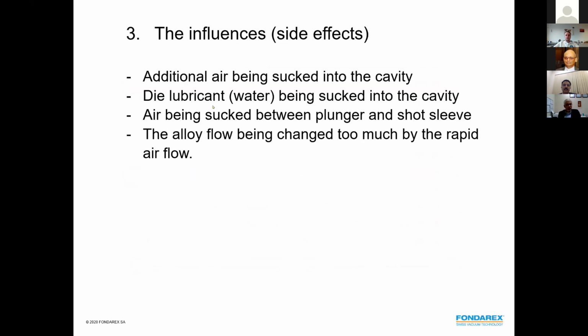So we are looking at different influence points. We have additional air being sucked into the cavity, often a big problem. Die lubricant, mainly water, being sucked into the cavity or already inside the cavity, and actually the volume which we have to take out of the die, the gas volume, will become much higher. Because if the water gets in touch with the hot mold or with molten metal, it's kind of like an explosion. It gets up to 200-300 times its volume. And all this water, H2O, or later on hydrogen, is a big problem inside the cavity.